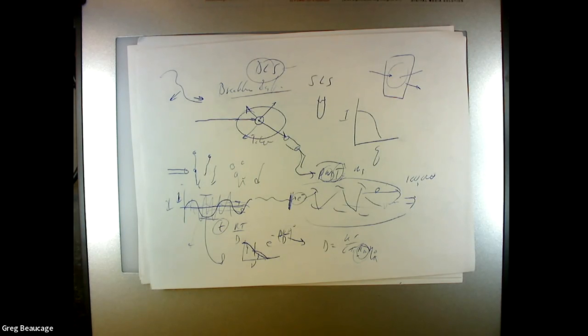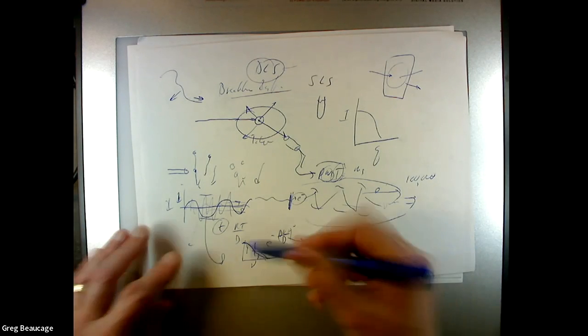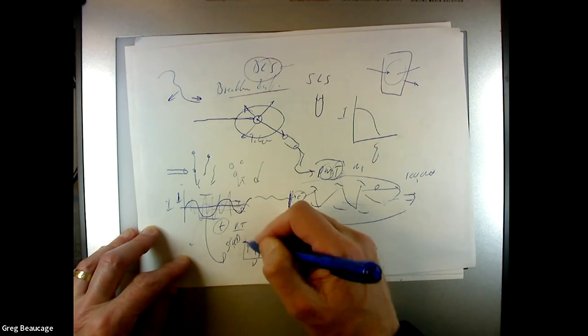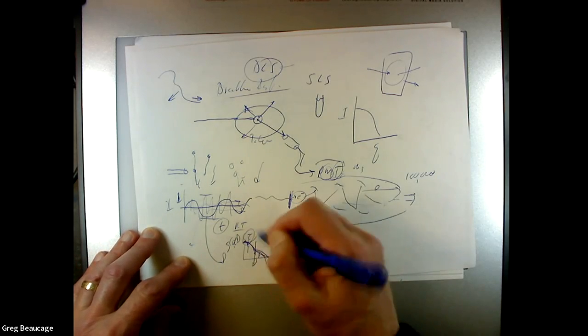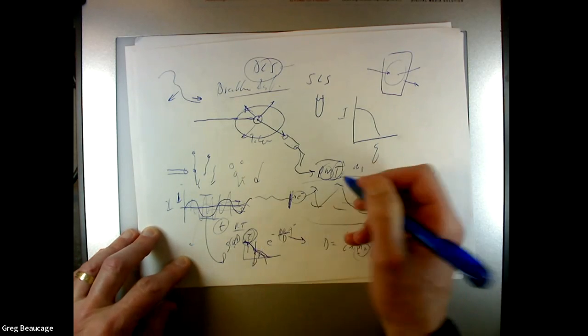In other words, this plot of intensity or transformed intensity, which is a correlation function in space and time versus frequency, gives you a relaxation time. Each one of these is going to be an exponential decay. That's the relaxation time. So you get a relaxation time from this machine. If you do this with different kinds of radiation, you get smaller time scale relaxations.